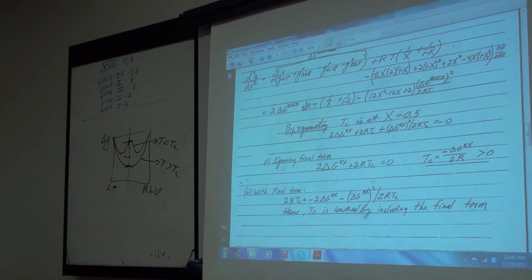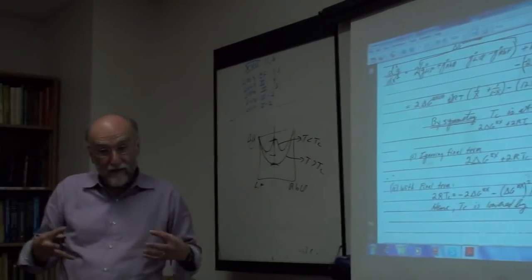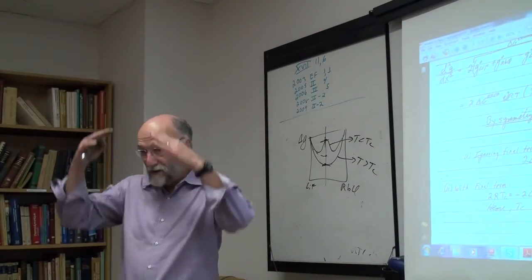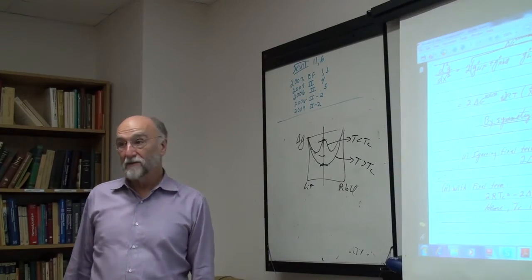Okay, and the reason is then that the critical temperature is because the rubidium fluoride and the lithium fluoride don't want to mix. The rubidium likes to stay next to the fluorine, the lithium likes to stay next to the chlorine. If you make a mixture, you're forcing them to be next to the neighbors they don't want to be next to, so they make a miscibility gap. But if you permit some non-randomness, then within the actual single-phase region, the rubidium and fluorine can cluster, the lithium and chlorine can cluster, they can stay next to each other without having to separate into two phases so much. So it stabilizes the liquid and they lower it.